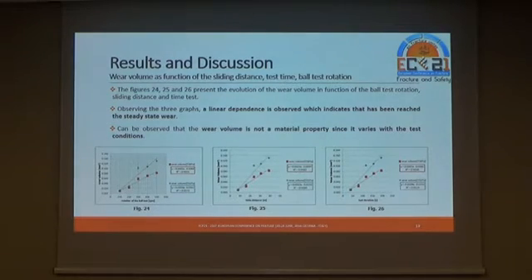Figures 24, 25, and 26 present the evolution of the wear volume as a function of ball test rotation, sliding distance, and test time. Observing the three graphs, a linear dependence is observed, which indicates that steady state wear was being reached. It can be observed that wear volume is not a material property, since it varies with the test conditions.